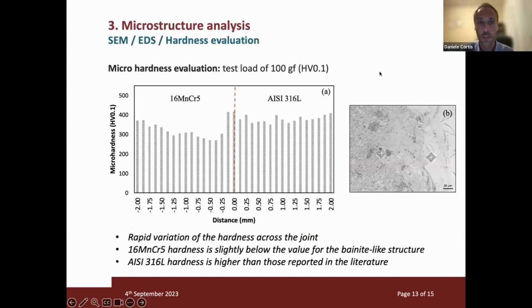Finally, we did an evaluation of micro-hardness with the Vickers load test, and with this plot we can see a rapid variation of micro-hardness. Of course, micro-hardness is a very complicated test in this case because you can find some porosity under the surface of the specimen that changes the value that you measure. Talking about the two different steels, for the case hardened steel we find a value of hardness slightly below the value in literature. On the other hand, for the AISI 316, the value is slightly higher than the literature.